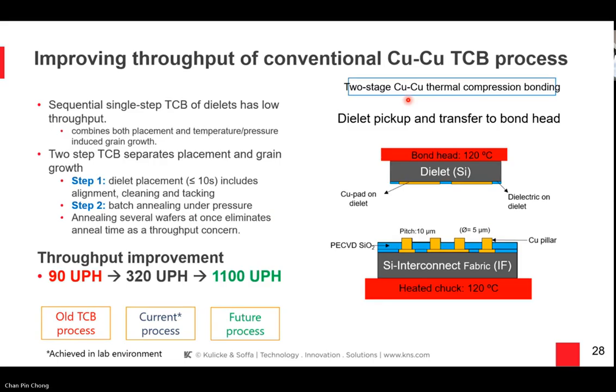Yeah. So now, how do we do this? One of the big issues in thermal compression bonding is that the throughput is something to be concerned about, because each die has to be cleaned in situ, placed in situ, and aligned. The alignment process does take a long time, and it is done at relatively high temperatures, 120 degrees Celsius. And this is the Achilles heel of thermal compression bonding.